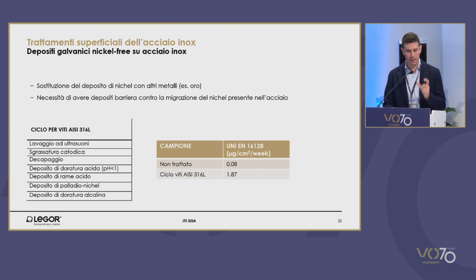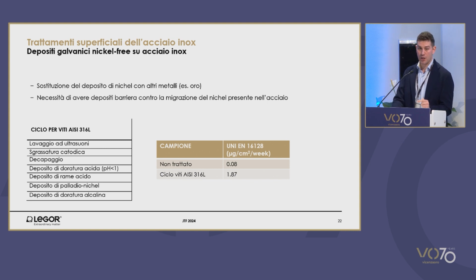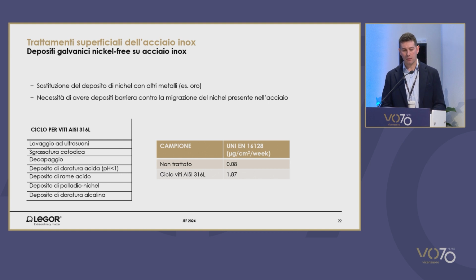What is difficult is making sure that the anallergic feature is maintained. When you scratch the chromium oxide on the surface, sometimes you also remove the barrier that you have in stainless steel, safeguarding the object from releasing nickel. So by means of nickel-free electrodeposition, you have to remake this barrier effect so as to contain the potential release of nickel.